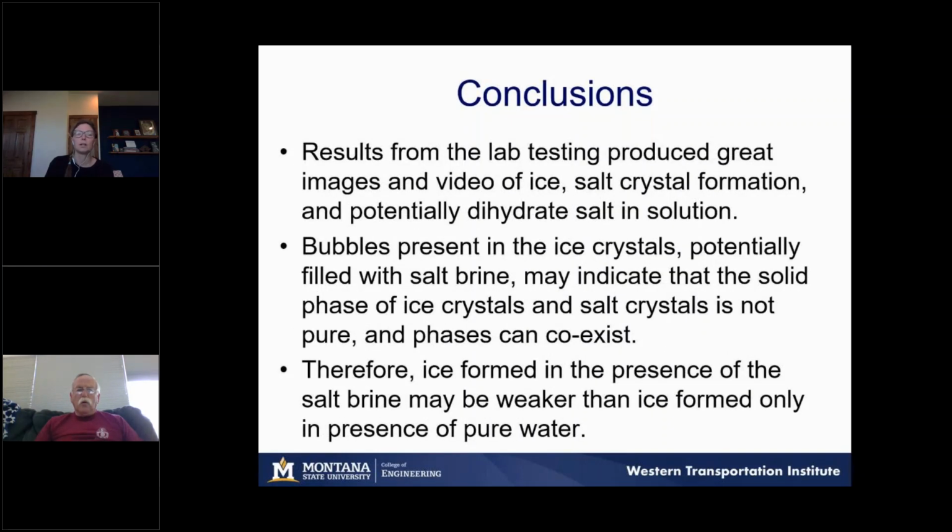Results from the lab produce great images and videos of ice and salt crystal formation, and also potentially dihydrate salt in solution. We also found that these bubbles present in the ice crystals could potentially be filled with salt brine, and this may indicate that the solid phase of ice crystals and salt crystals is not pure, and phases can coexist, so liquids and solids together. And this kind of reinforces earlier work by folks in Norway that suggests that when ice forms in the presence of salt brine, it actually forms a weaker ice. So in theory, it may be easier to break apart.